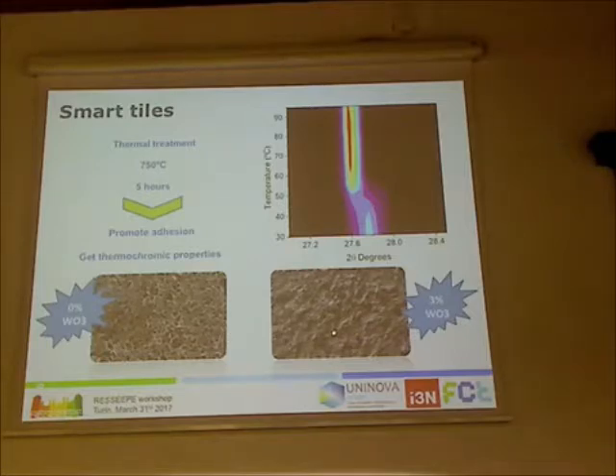This is how the particles look on top of the tile, whether with 3% tungsten oxide, as I mentioned, to decrease the critical temperature, or without any tungsten oxide. But the most important thing is that in this case, they stay there.